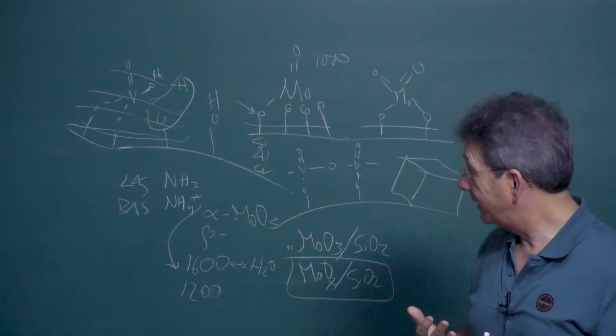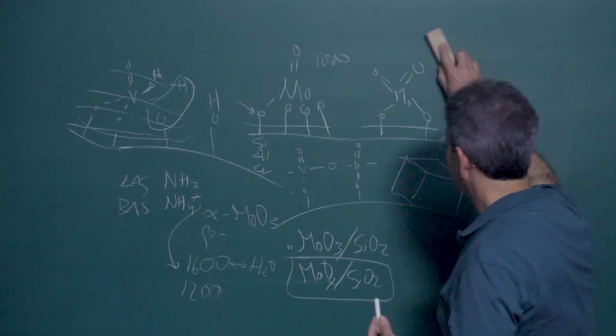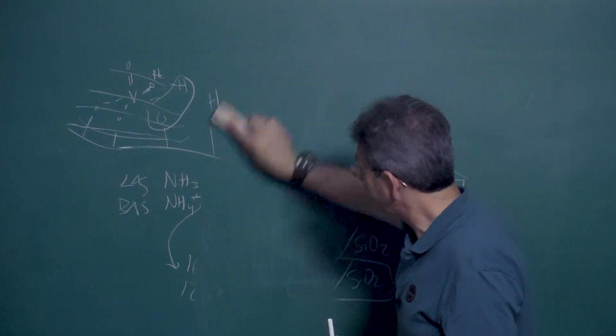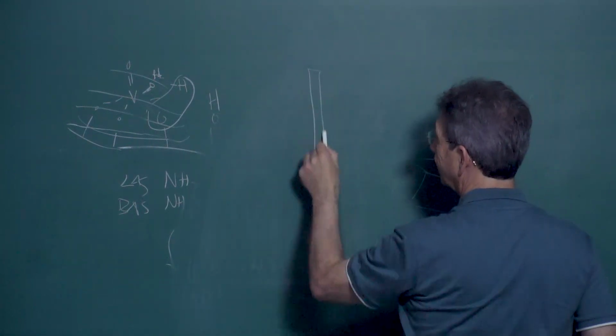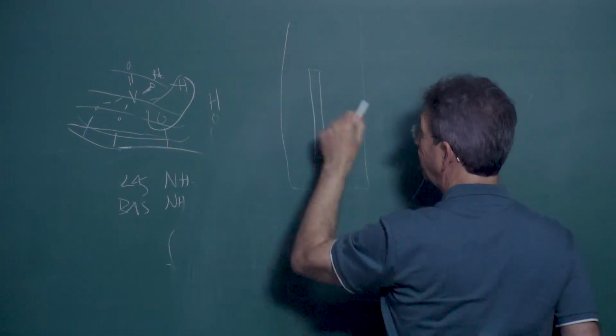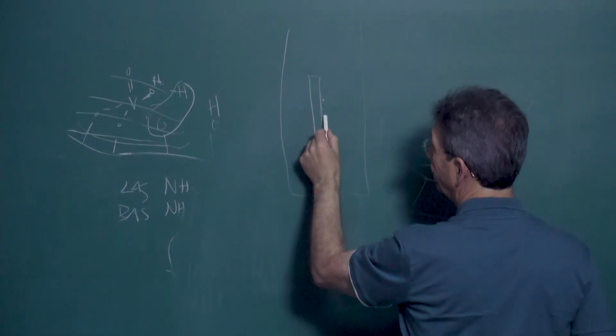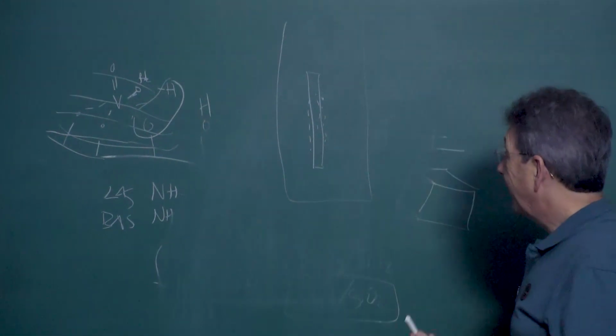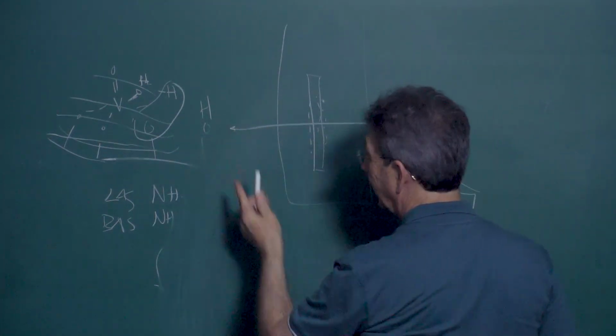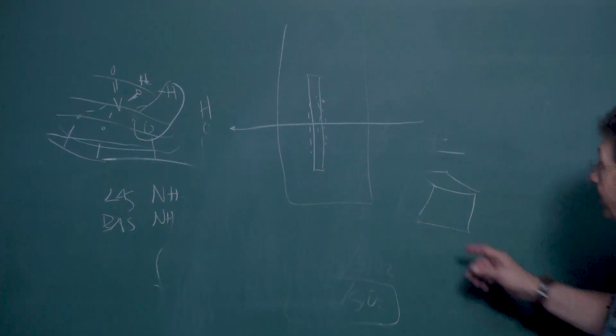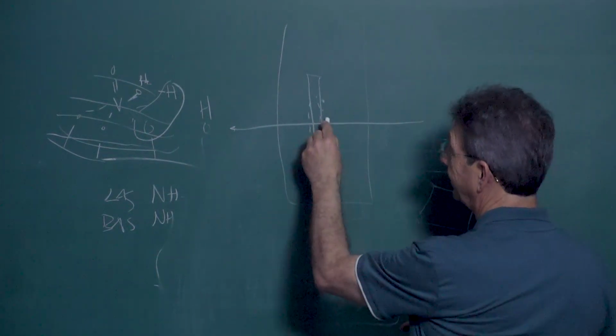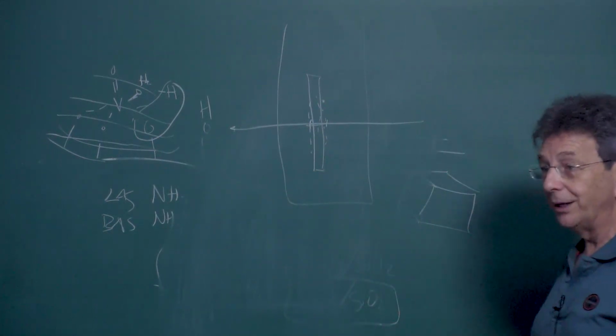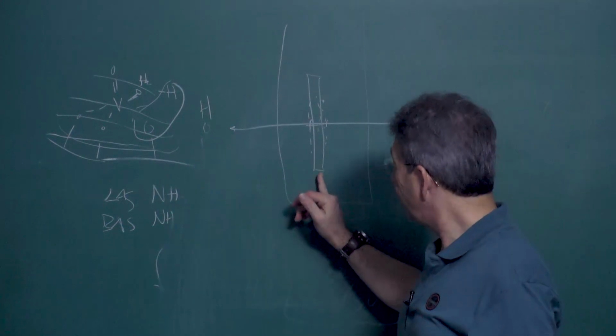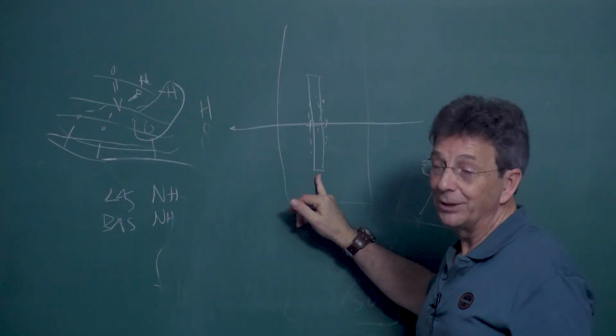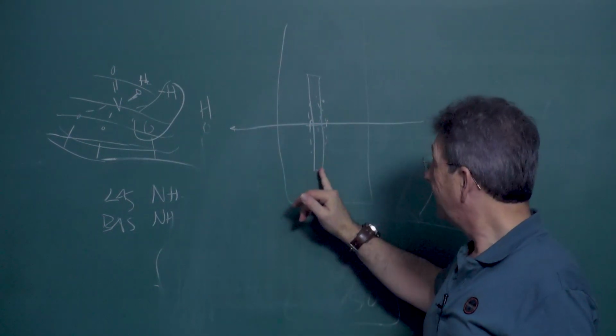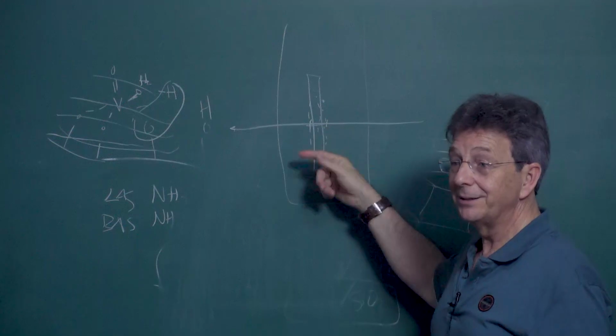But the nice thing is that when you have the infrared wafer inside the cell and you are exposing it to whatever, the molecules absorb over here and within the porosity of it. And in the end, you are making the infrared spectrum. Then the Beer-Lambert law applies. So whatever is being absorbed will depend on the path, on the concentration, and on the extinction coefficient of the sample. So you must always know the thickness of your sample. You can calculate it by density, and you can normalize the intensity of these pyridine bands based on that.